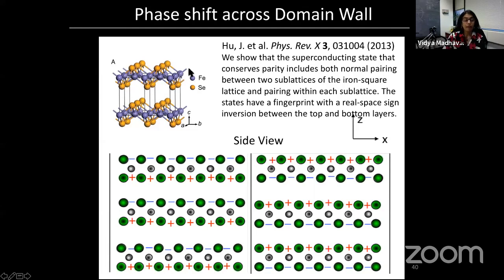So if you can find those kinds of regions where you have this shift in the selenium atoms, a half unit cell shift, then according to this theory at least, you should see a pi phase shift in the superconducting order parameter.